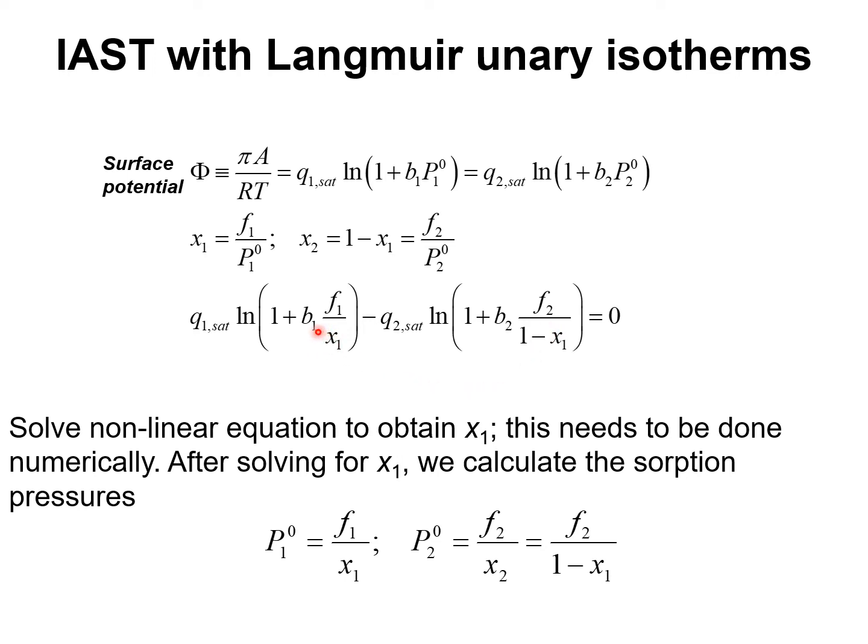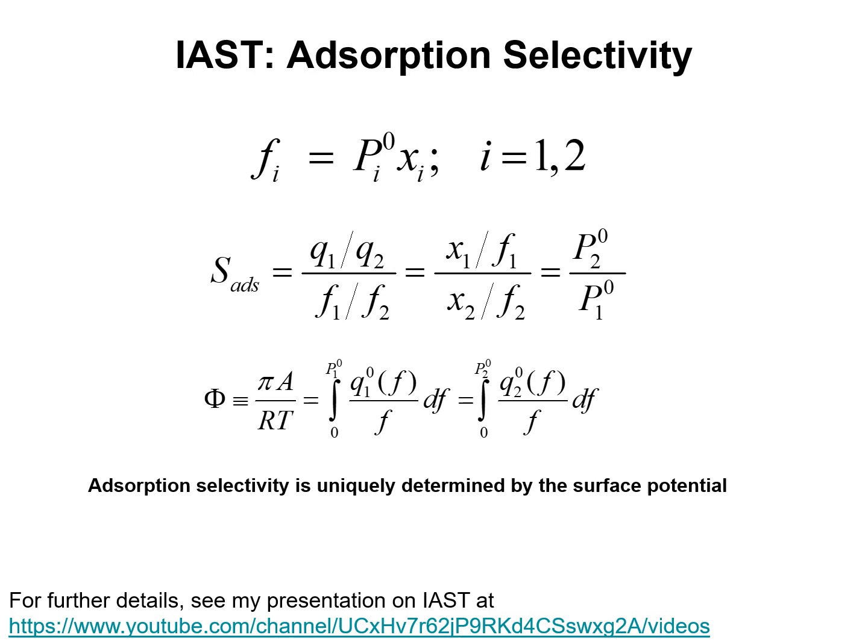And after solving this equation for the mole fraction x1, we can determine the sorption pressures by use of these expressions here. There's a further point to be made regarding the adsorption selectivity. The adsorption selectivity is defined as the ratio of the molar loadings to the ratio of the partial fugacities in the bulk fluid phase.